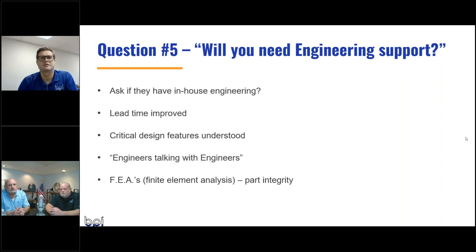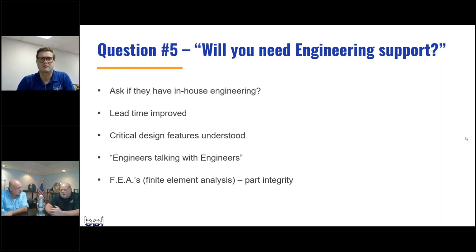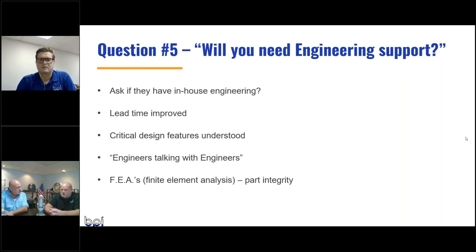In the FEA, we're looking at the flow — making sure it's not turbulent, looking at the solidification patterns to make sure it's flowing from the coolest portion of the tool, which would be the center, to the gating system. You want to keep your gating system hot. If there's any strength associated, you can look at stress in the casting where you don't want it using FEA tools.